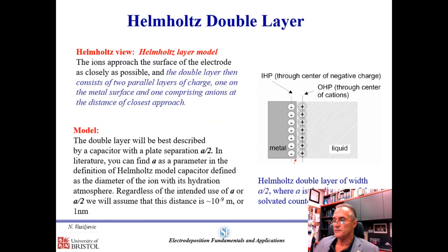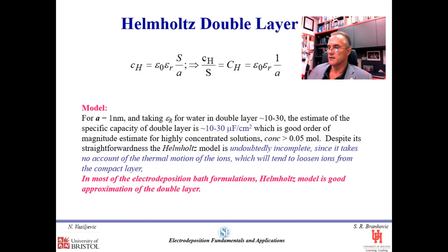Now, one of the models of the electrified interface is called the Helmholtz model, and it's a simple parallel plate capacitor model which assumes that the electron spillover from the side of the metal is met by a charge of the opposite sign from the side of the solution, as two parallel plates. The distance between the plates is of the order of 10 to the minus 9 meters, and the capacity of this parallel plate capacitor could be calculated in terms of the dielectric constant of free space, water, and the distance between them, as 1 over A here.